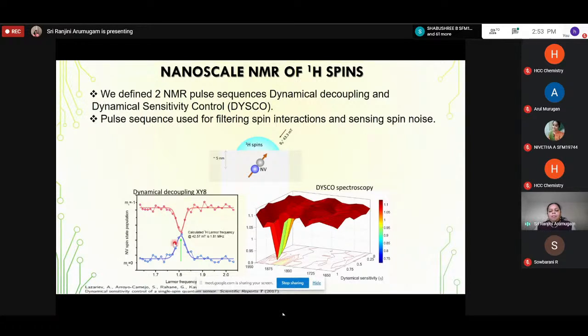The pulse sequences are used to filter the spin interactions and sense spin noise. In the dynamic decoupling method, we could see the proton coming into resonance at 1.81 megahertz at the field of 42.57 millitesla, which is exactly what you see using a regular NMR experiment. The advantage here is you can see the proton spins. We are now doing this for various small molecule systems, and we are expanding this technique to other molecular systems. This work is published, and other works are in progress. In this system, the proton spins are very sensitive, and very clearly you can see them.